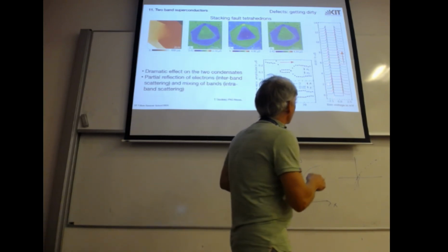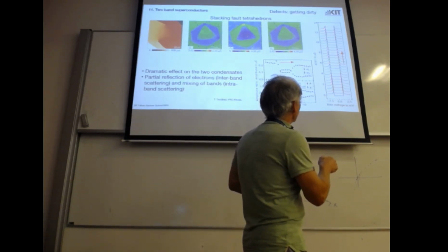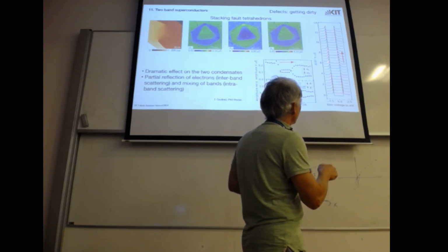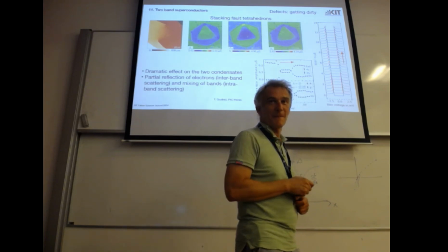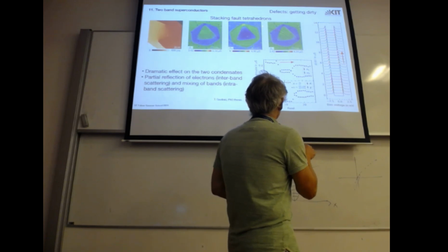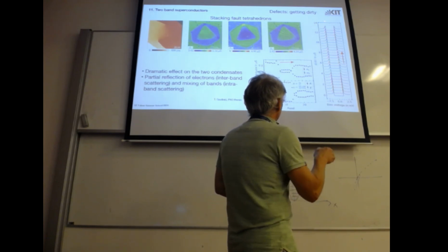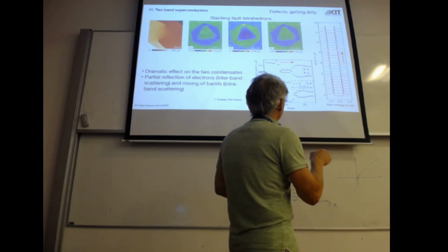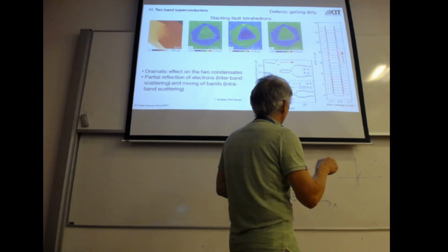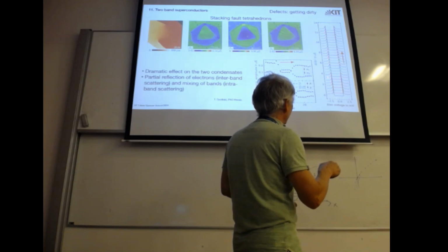You can hardly see it, but here outside you see the two bands, two peaks, and then you see that one peak here shifts a little bit to the right. There's a cursor at various positions. Yeah, these are these points here. That's a strong shift. On this defect-free sample, we see the two gaps, and then they come together to one gap, shift in energy, and shift again to one gap.